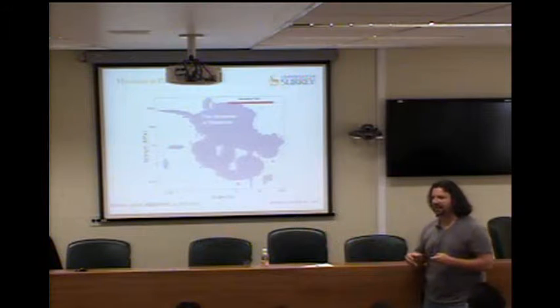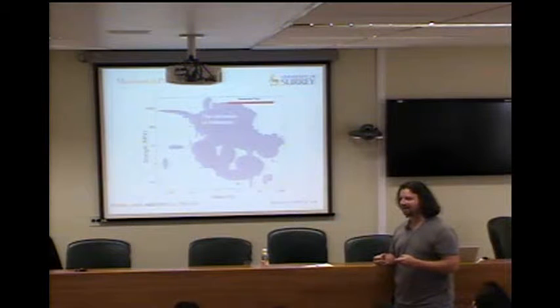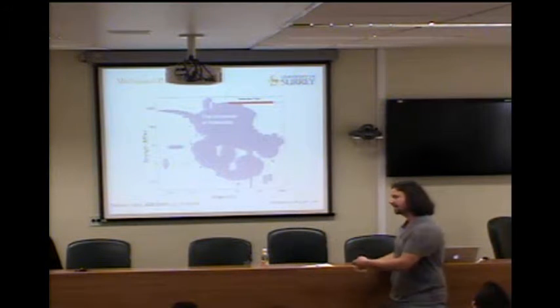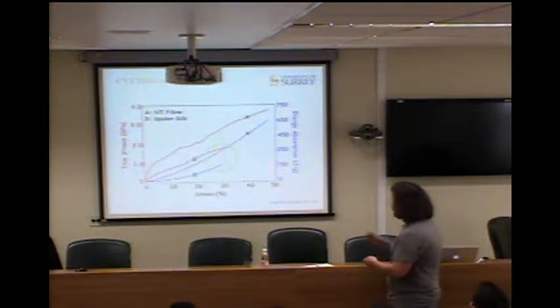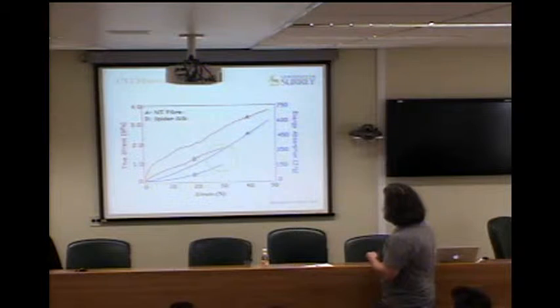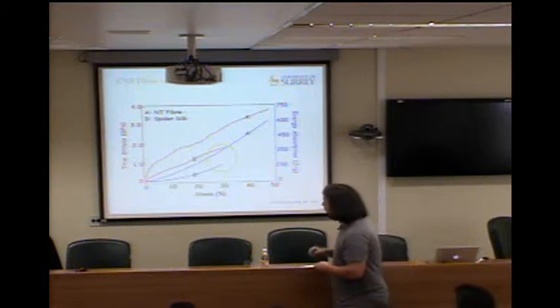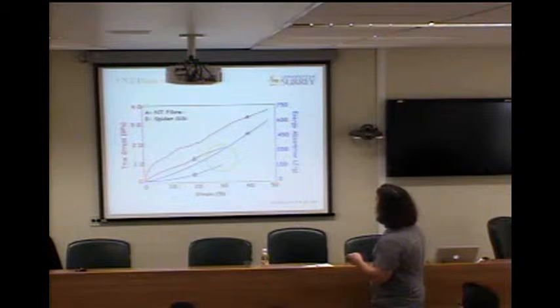And the reason for that, I won't go into it today, is that the dynamics of the carbon nanotube and polymer interaction at the nanoscale is very similar to protein-protein interactions in spider silk. So it's kind of utilizing the building assemblies of nature, but using wholly synthetic systems to do it. And this is just a quick comparison, I don't want to go into this too much, of the energy absorption compared to spider silk. One can see for stress, the strength, the amount of force applied before the fiber breaks, for nanotubes, it's close to 4 gigapascal. For spider silk, it's 1.8.